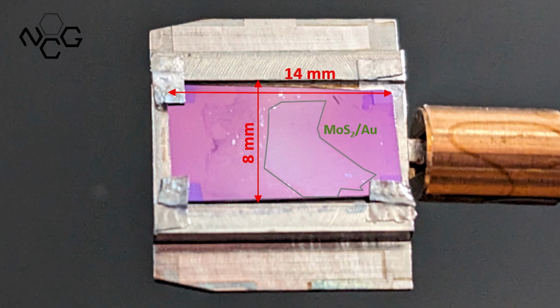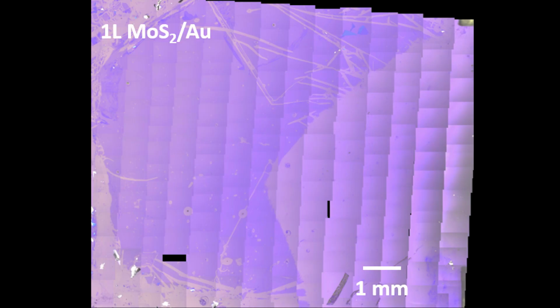To prove our system, we started with the exfoliation of MoS2, or molybdenum disulfide, on gold. This has already been demonstrated in air, so it was important to reproduce it in UHV. We obtained monolayer MoS2 flakes of several millimeters in size and of high quality, with few defects only due to the parent MoS2 crystal. More interesting was to demonstrate MoS2 exfoliation on silver.